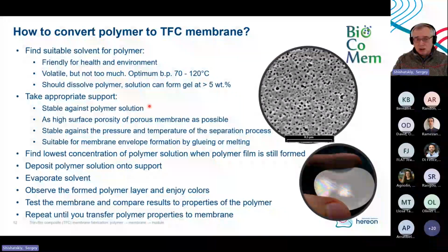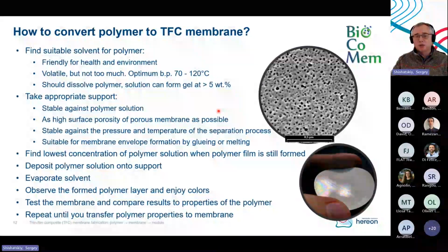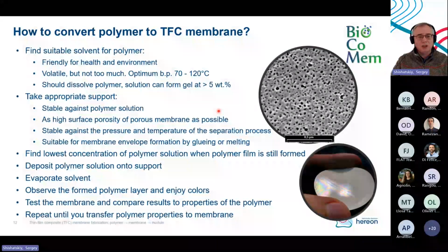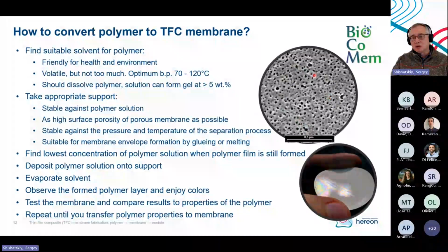Of course, it should be stable against the polymer solution. It should have as high surface porosity as possible, be stable against the pressure and temperature of the separation process where it should be applied, and be suitable for membrane envelope formation by gluing or melting. And on the right, you can see the surface porosity of our standard polyacrylonitrile membrane, which can have surface porosity up to 13%. That's all we can get. That's why it's necessary to have a gutter layer on top of this porous support. Please have a look at what a gutter layer is.